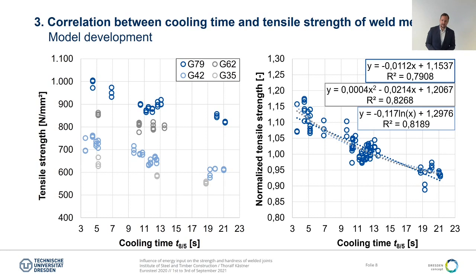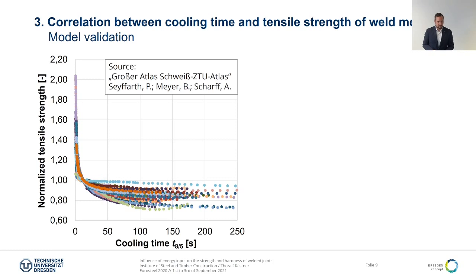So within the next step, we decided to compare our results to results from the literature. Again, the normalized tensile strength with regard to a cooling time of 12 seconds. And now, as you can see here, we have a larger spread of the cooling times. These are the results of so-called time temperature transformation examinations, which are from the literature.